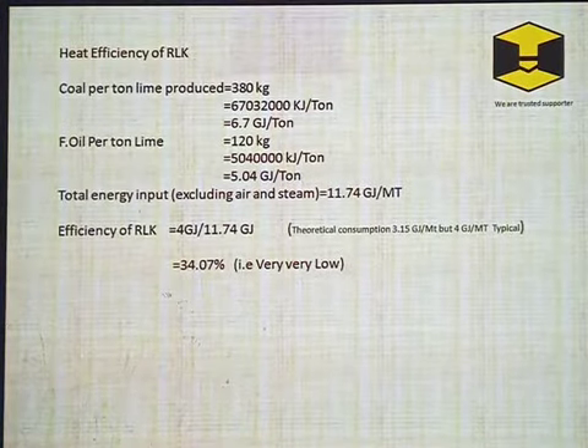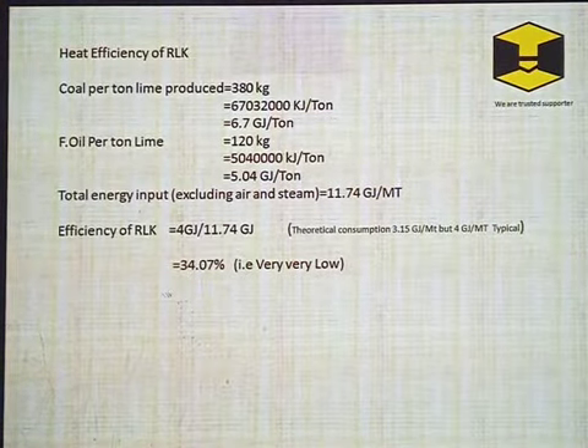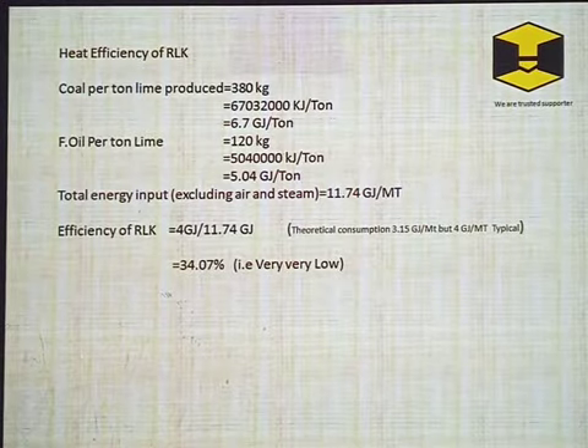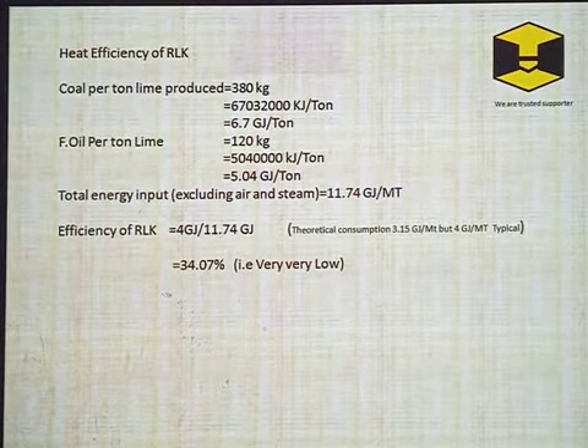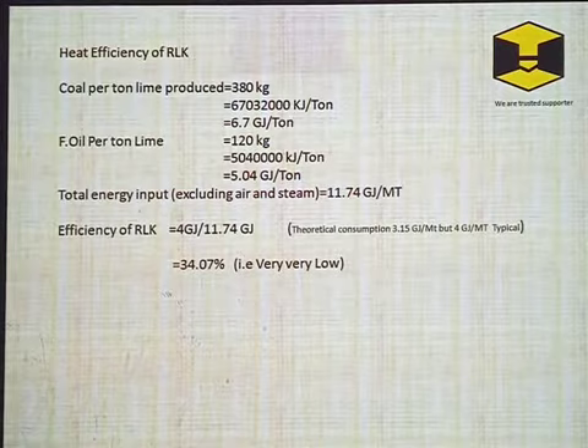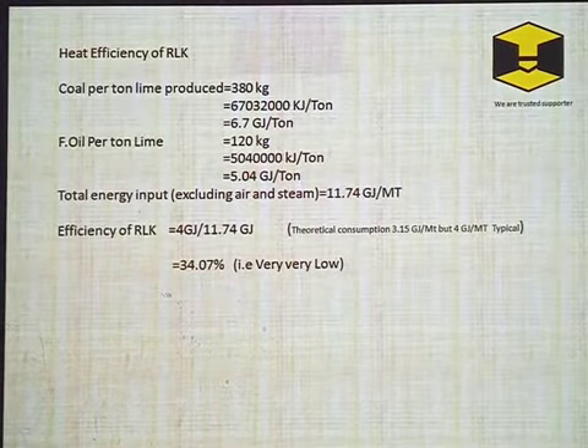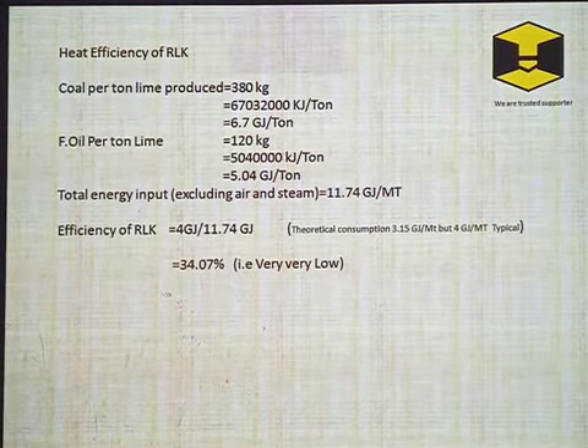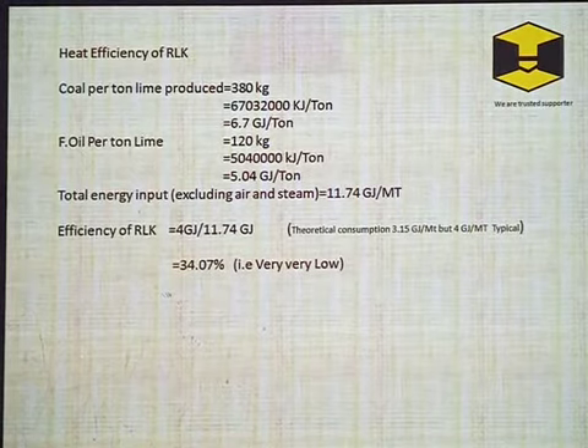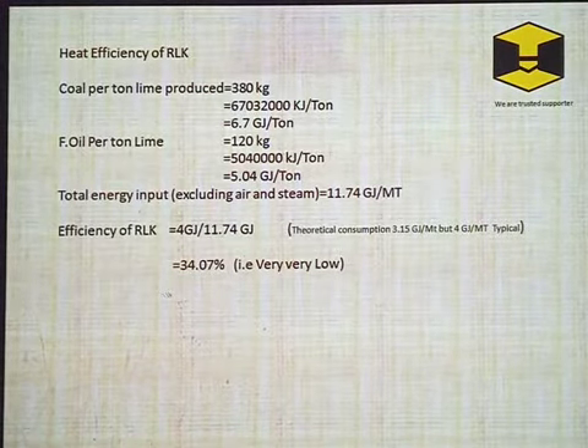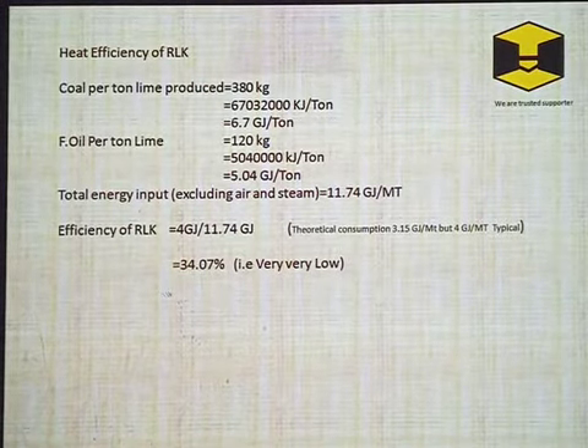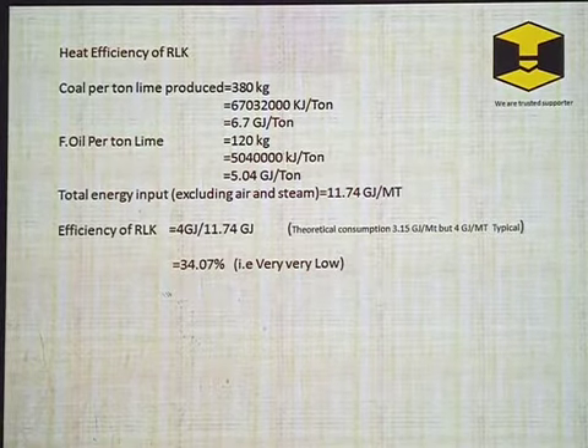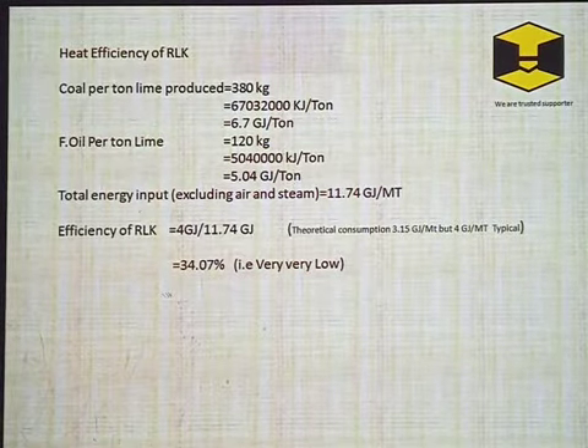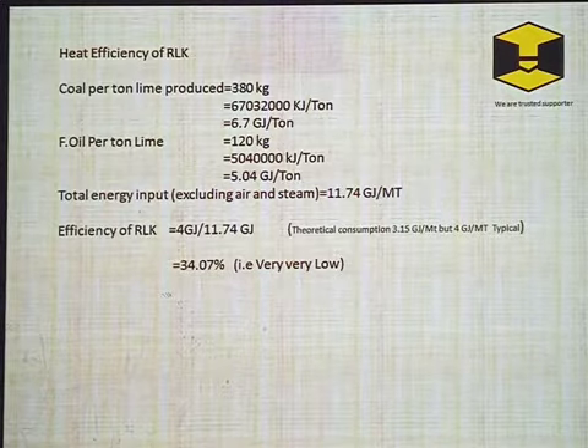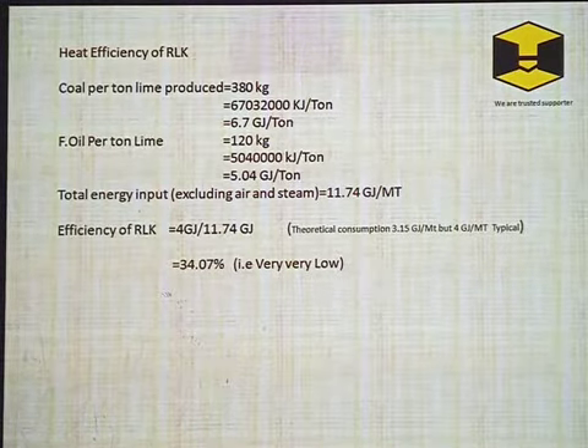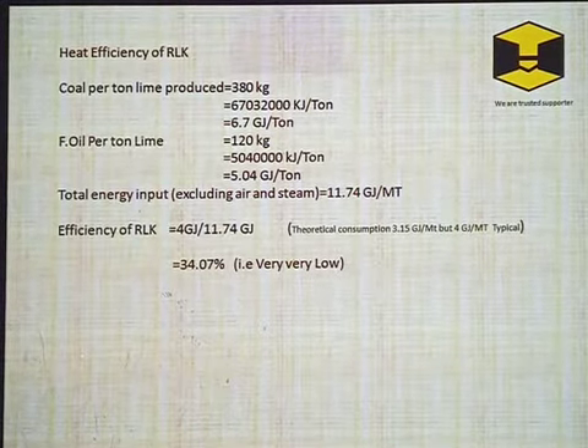Here is the heat efficiency of rotary lime kiln. So every metric ton lime produced in rotary lime kiln requires 380 kg coal along with 120 kg per metric ton furnace oil. So total input is 11.74. So efficiency is 34.07, which is very low. But efficiency in rotary lime kiln can be seen as low as 20%.